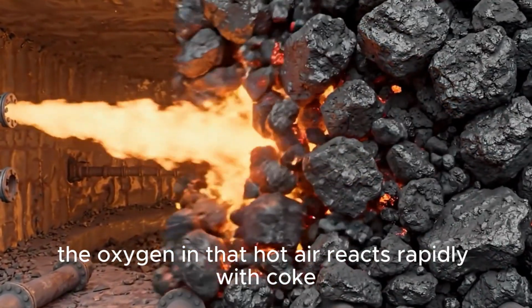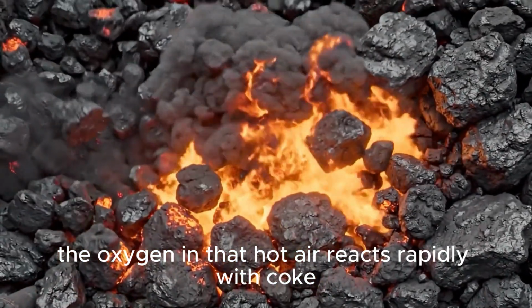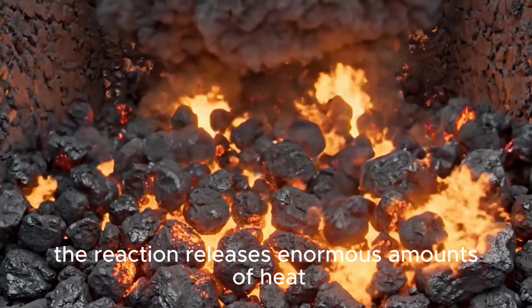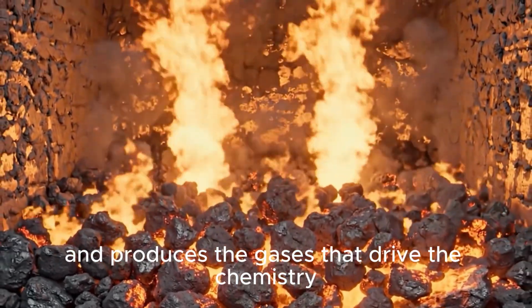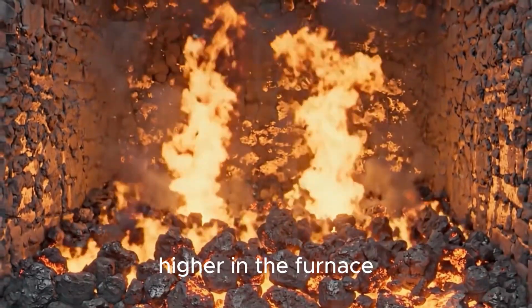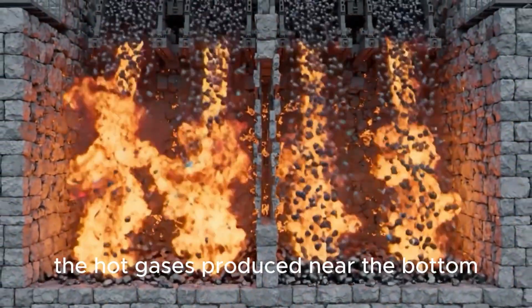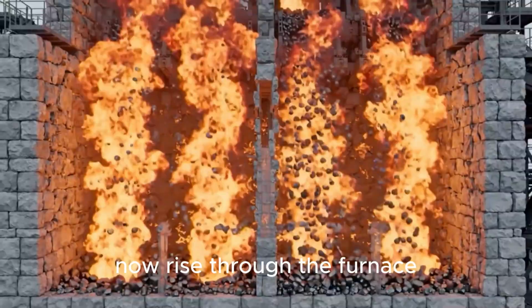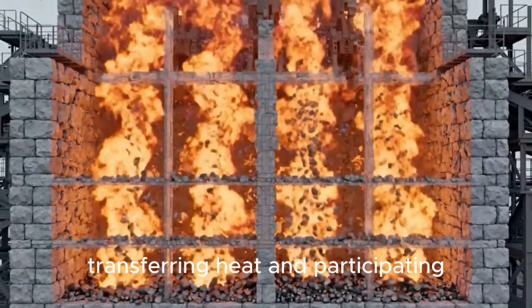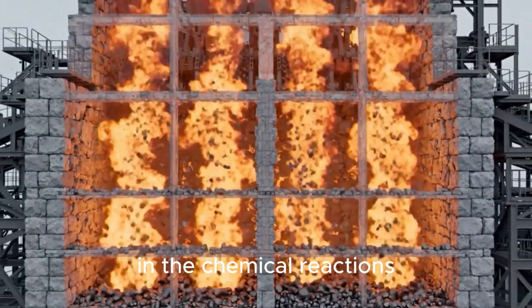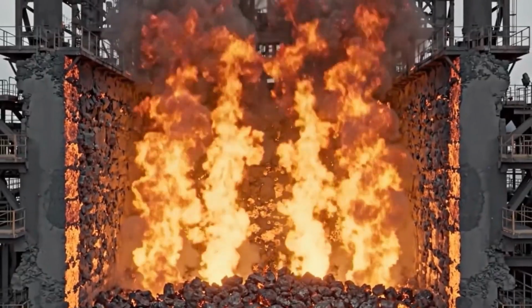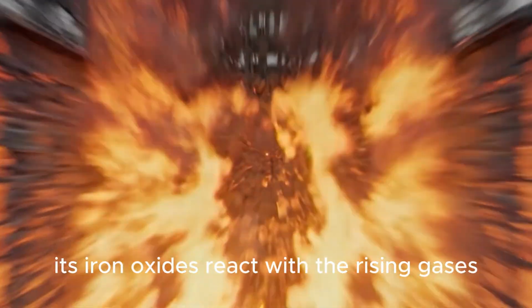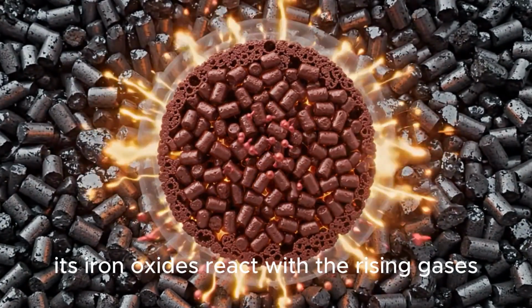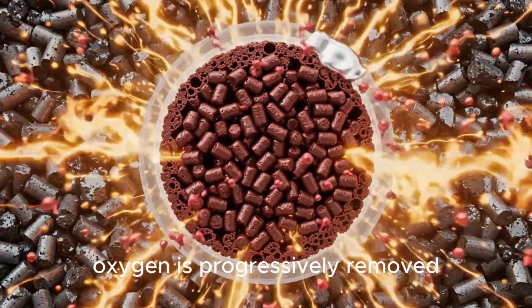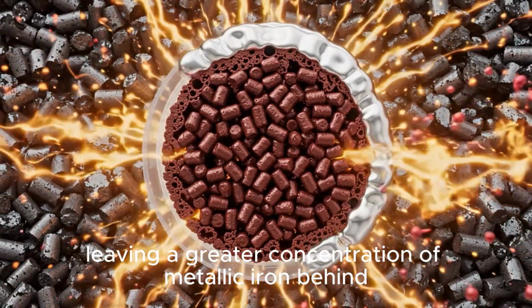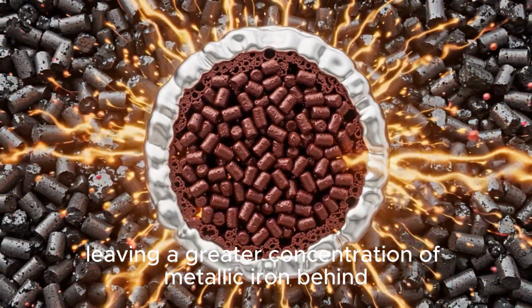The oxygen in that hot air reacts rapidly with coke. The reaction releases enormous amounts of heat, and produces the gases that drive the chemistry higher in the furnace. The hot gases produced near the bottom now rise through the furnace, transferring heat and participating in the chemical reactions that gradually transform the ore. As the ore moves downward, its iron oxides react with the rising gases. Oxygen is progressively removed, leaving a greater concentration of metallic iron behind.